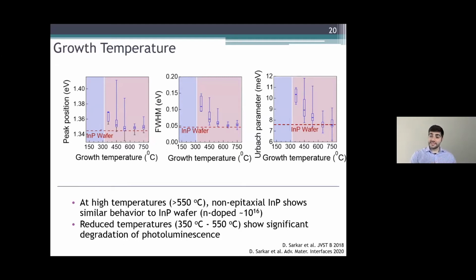We're showing some statistics of indium phosphide grown on non-epitaxial substrates as a function of temperature. And what you see is that if you look at the higher temperature materials, the peak position is pretty similar to what you might get from an indium phosphide wafer.